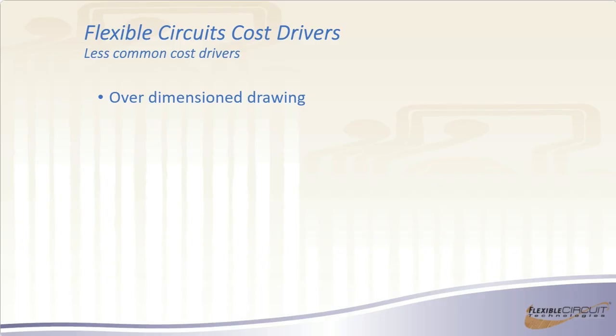So last time the guy called, I said, throw them in an oven for 15 minutes at 250 degrees and remeasure them, and they shrunk right into tolerance. But I guess the long and short of that story is there's no reason there should be a tolerance like that on a flexible circuit. It is a flexible circuit. By all means, if you have a critical dimension, put it on your drawing. If it's not critical, don't put it on, because if it's on the drawing, we have to verify it, and that will have a cost associated with it.